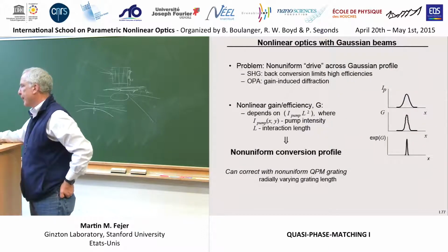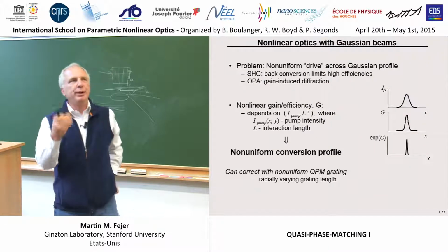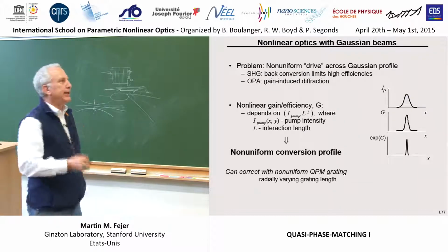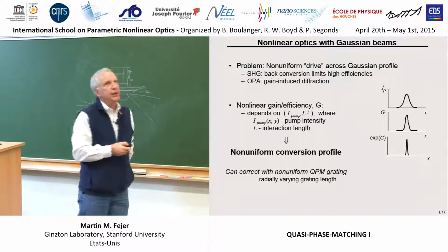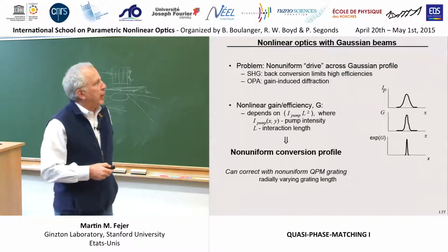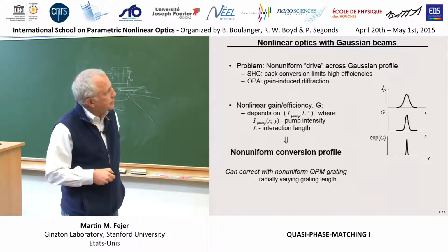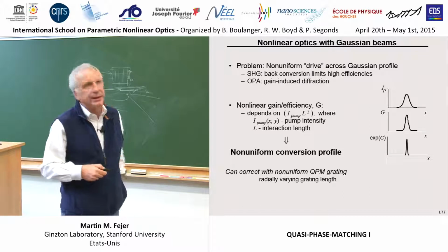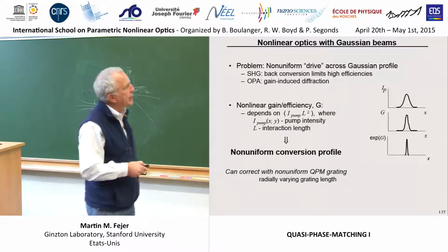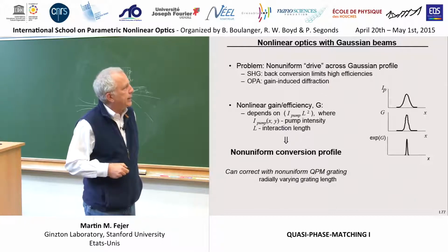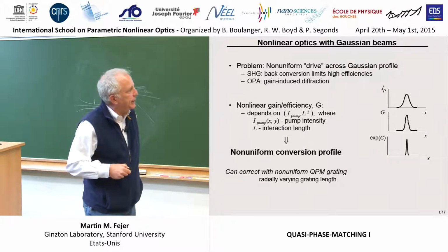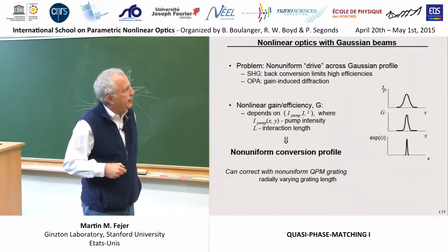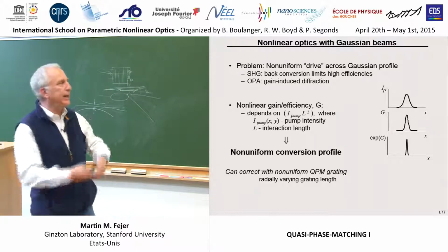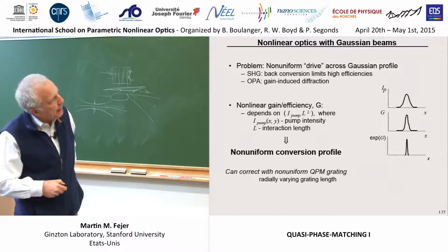So when you build a high-gain nonlinear device, for example, the OPA that Benoit talked about in his LBO crystal, there's a bit of a problem because your pump intensity, unless you've engineered a flat top in space and time, is a Gaussian. The exponent is proportional to the intensity. And if the peak of this thing is large, then when you exponentiate it, it's much narrower than the original pump beam. The amplification of your OPA, the efficiency of your SHG process, whatever you're talking about.